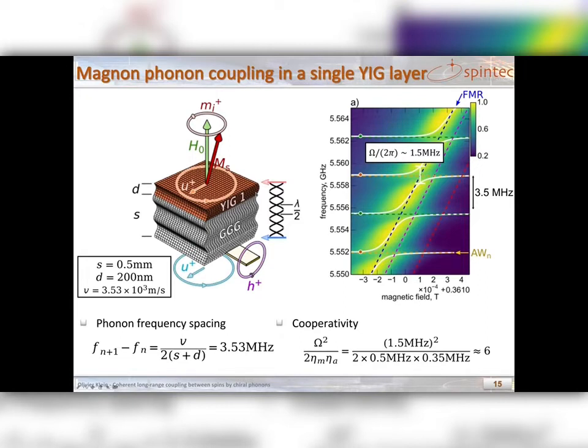More specifically, that means that half a wavelength times an integer should fit the total thickness of a crystal, which gives the following frequency spacing through this formula, and this is very close to the measured value. We can also calculate the cooperativity with the coupling strength and relaxation rate, measuring here the anti-crossing, and we get a cooperativity of about 6, which is very good.